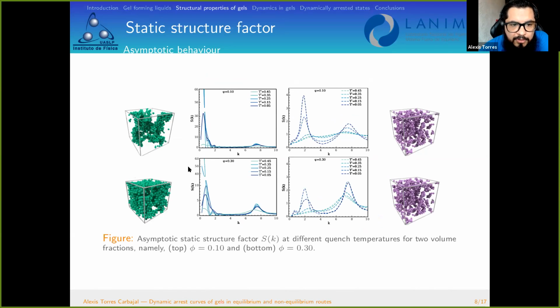In this scenario, for example, we observe some snapshots of the system. In the case of a packing fraction or volume fraction of 0.1, we observe at a certain temperature, for instance 0.35, a full phase separation. But if we continue decreasing the temperature, we observe that the Lennard-Jones system expands and forms a network that is very compact. In contrast, the Lennard-Jones Yukawa fluid doesn't form this kind of compact structure, but we also observe some kind of formation, at a very low temperature, in contrast with the Lennard-Jones.